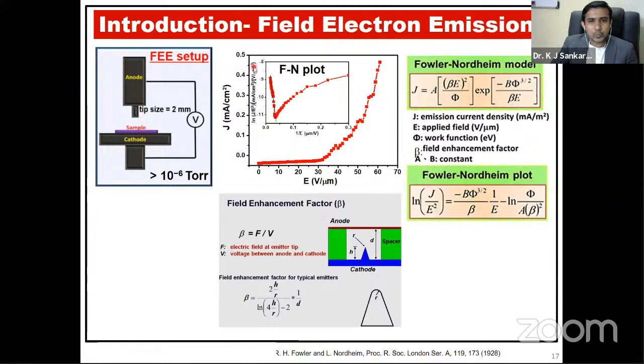Also, from the FN plot, we can calculate the field enhancement factor. The field enhancement factor is a beta factor which can be obtained from the electric field at the emitter tip divided by the voltage between the anode and the cathode. This field enhancement factor will be improved if you have a nanostructuring of your material. I will also explain about the field enhancement factor in my work.